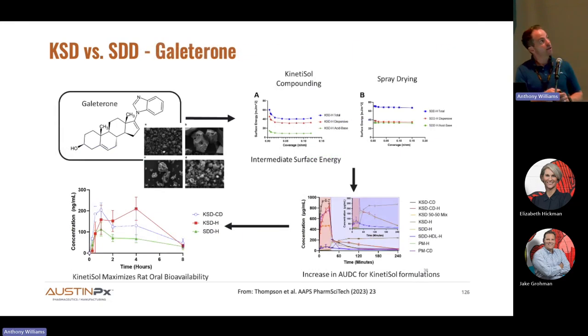So to carry the galeterone, just as a last case study, this is the graphical abstract from the paper. I like it because in one slide, it summarizes the whole thing. We took galeterone, we made a KinetiSol dispersion in HPMCAS, we made the equivalent spray dried dispersion. You've seen these graphs. This equates to, once again, in vitro release, where the KinetiSol material prevents acid phase release and promotes intestinal phase free drug. And once again, the punchline, as always, we do an oral bioavailability study and it shows superiority of the KinetiSol material relative to the spray dried dispersion.